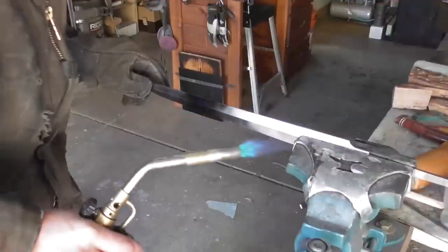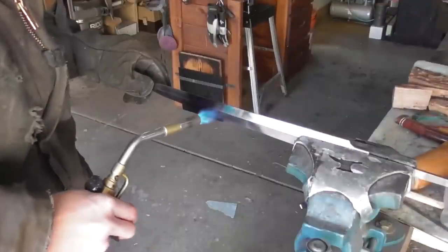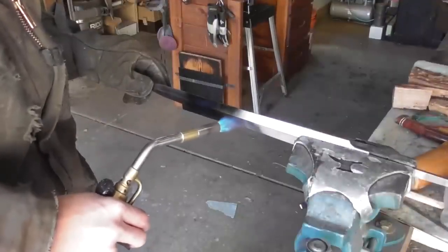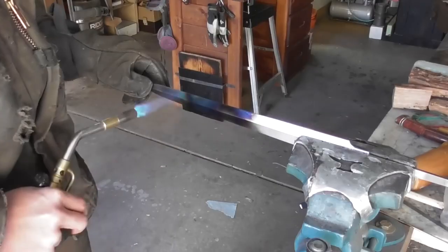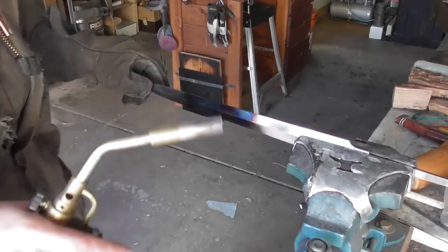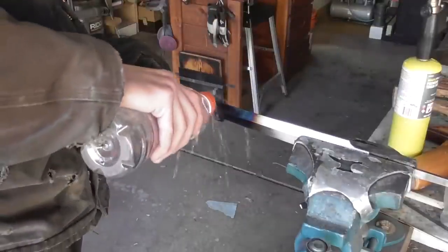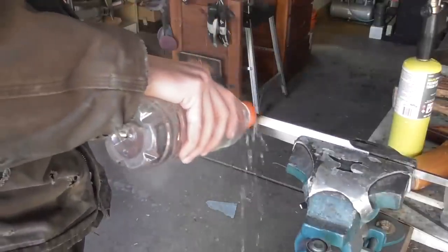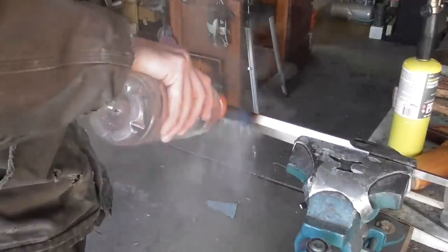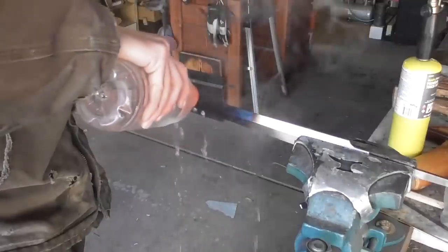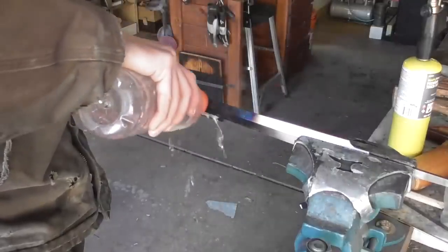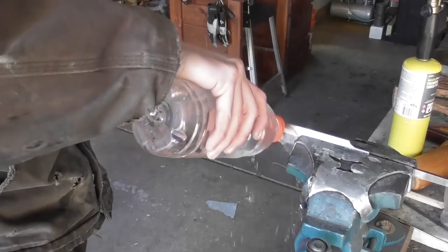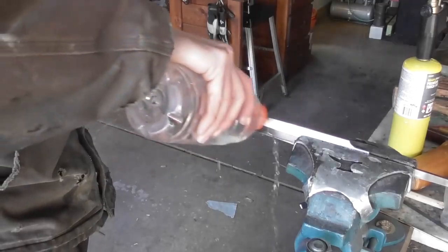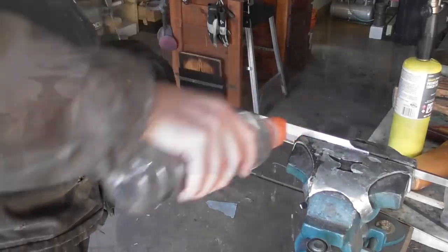The blade is just about ready to heat treat. What I'm doing here is just getting out some of the minor warps pre-heat treat. I found that when you do that before heat treatment and you have a straight blade, the odds that it warps after heat treatment are a lot lower. A lot of times it's going to warp inevitably, especially when you have a thin blade like this that's this long, but I like to do it beforehand. I don't know if it actually does anything, but I feel like it ends up being straighter afterwards.